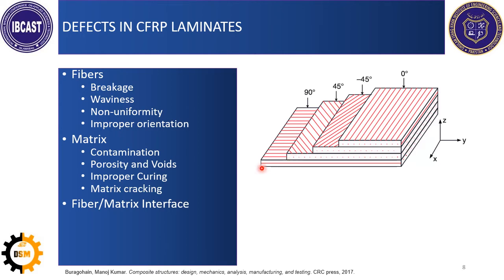The next one is matrix cracking. If you have cracking within the matrix, it can be because of some other issues, like very small micro cracks. These are much smaller than voids and porosity, but these micro cracks can initiate, propagate, and then result in the failure of the composite laminate. So these four are the common defects in the matrix.